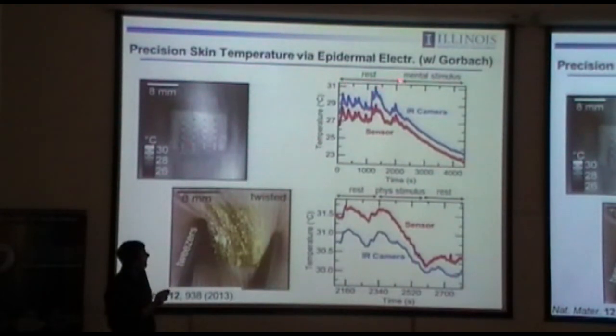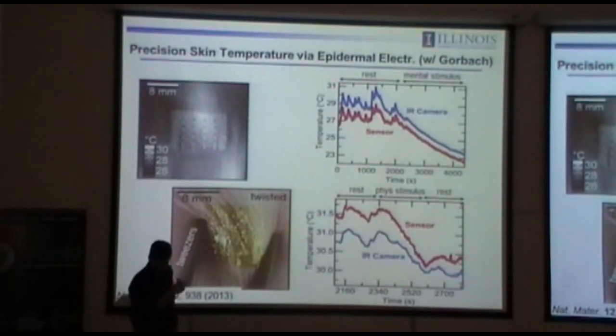Now what happens is after a period of rest, the individual is asked to start to do mental math. So this is subtraction and division done in the head, without pen and paper. And what you see is there's an immediate systematic decline in temperature. That's because you start to induce firing of individual sweat glands, and that begins to cool the skin by a very minor amount. But you can determine something about cognitive state then by measuring temperature, not only these intrinsic oscillations, but overall systematic changes.